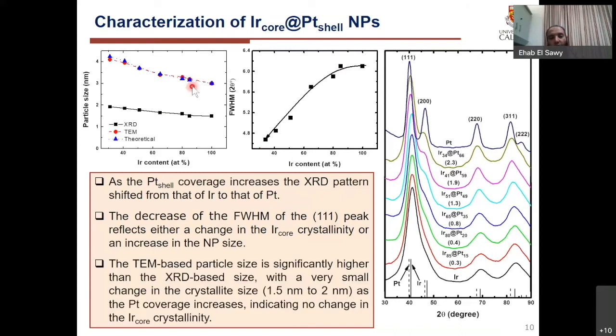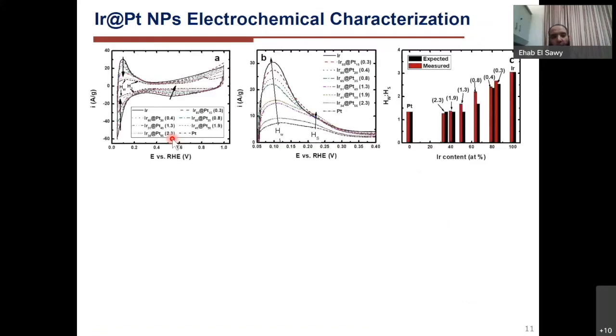So we compared the increase in crystallite size with the increase in particle size from the TEM, and the increase in particle size from the TEM matched very well with our theoretical calculation for the increase in size according to the number of layers we are putting on the iridium core. Because the change in crystallite size matches the trend, we assume there is no change in the crystallinity of the core while we put the shell on the surface. Due to the good match between platinum and iridium, there is no mismatch that may cause strain.